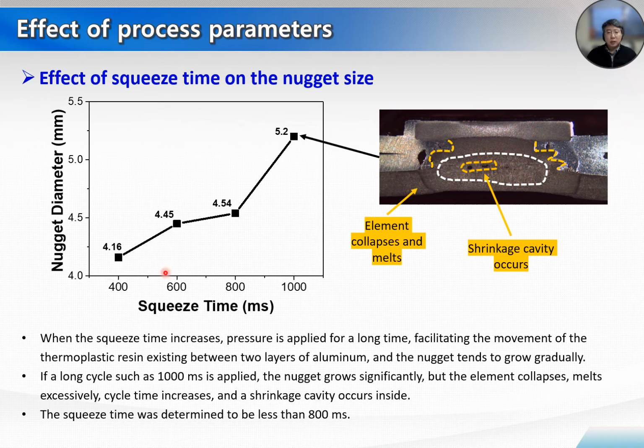When a long cycle, such as 1000 milliseconds, is applied, the nugget grows significantly, but the element collapses and melts excessively. As the cycle time increases, shrinkage cavities also occur inside. The squeeze time was determined to be less than 800 milliseconds. However, the mechanism of the effect of this squeeze time on the weld quality needs to be further investigated.